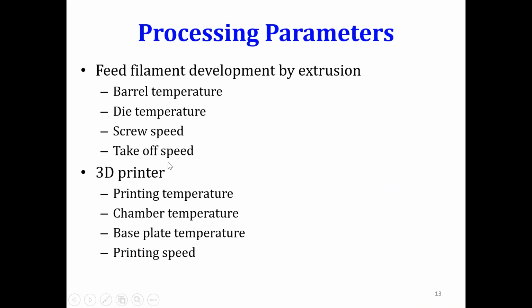So whenever we deal with any additive manufacturing methodology, in particular fused filament fabrication, you need to keep an eye on these different parameters. During extrusion, we need to tune barrel temperature and die temperature. These two are typically set with a baseline of Tg, the glass transition temperature, which should be known to you, the melting point, which should be known to you, and the polymer degradation temperature, which should be known to you.